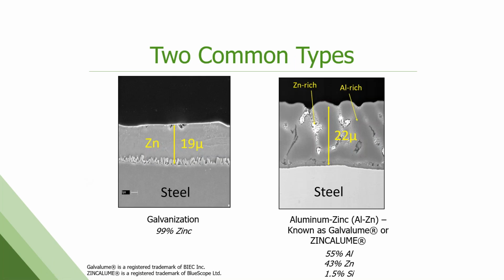This is a cross section at the microscopic level of what's going on with this product. On the left is hot dip galvanized, so it's straight zinc. You get these little alloy interface crystals that grow in it and bond the zinc to the steel surface. On the right is the aluminum zinc product. And I always think it looks a bit like a brain to me, right? So you get the gray matter and then you have these white parts.